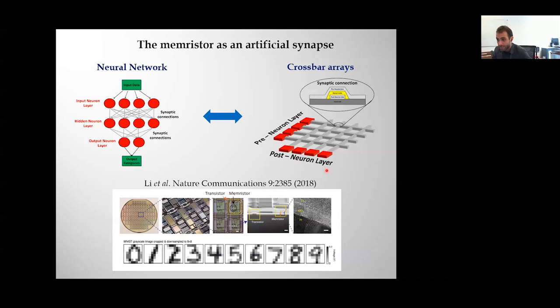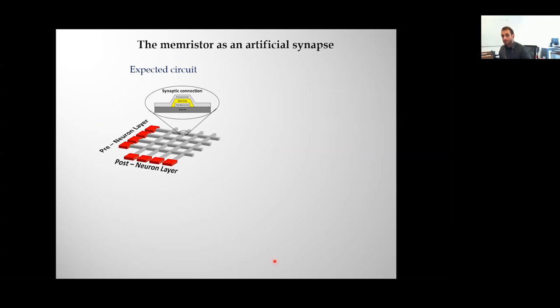If you go forward just 3 years, you can see the level of complexity, how fast the field evolved. So this is a paper from 2018, and here they are dealing already with wafer scale crossbar arrays that are very well integrated with transistors, so they can carefully adjust the weight of each synaptic weight. And in this case, they're able to take these images of handwritten digits. These are 64 pixel images, and this crossbar array is able to take this image and say, okay, this is a 7, just a handwritten image. So they really have done a lot of work, but there are problems to this.